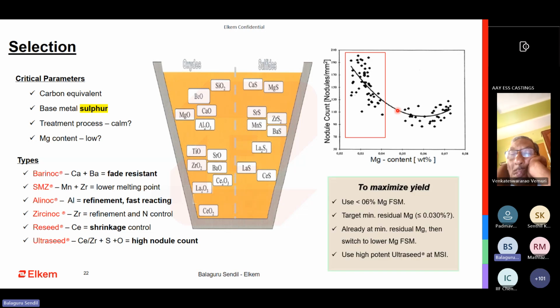So to summarize, for maximum yield, you have to go for a low magnesium FSM, preferably 6%. Is residual magnesium of 0.030 really required? Maybe we should operate at much lower levels. If you're already at 0.030, and you're using a 7% grade FSM, I would ideally request that you think about coming down to a 5% grade FSM and see whether you can optimize your yield.